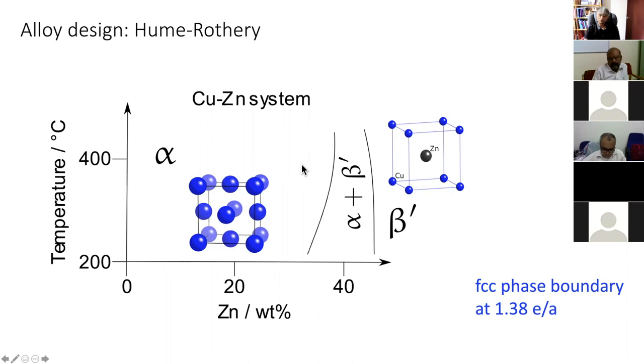So according to the Hume-Rothery rule, he discovered that when the electron atom ratio exceeds 1.38, you begin to get the precipitation of your beta prime phase. And in his time, it was thought that this particular electron to atom ratio corresponds to the point where the energy levels of the electrons touch a Brillouin zone boundary. Later on, that was shown not to be the case. Okay, so we regard these rules as empirical, but they work a lot of the time.